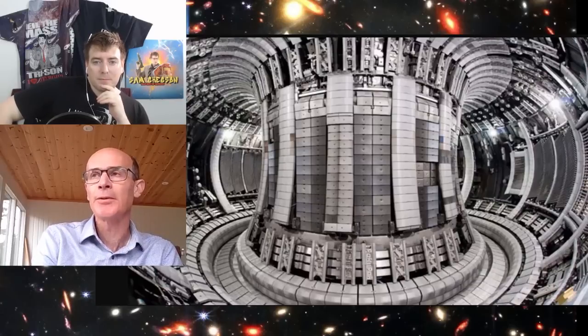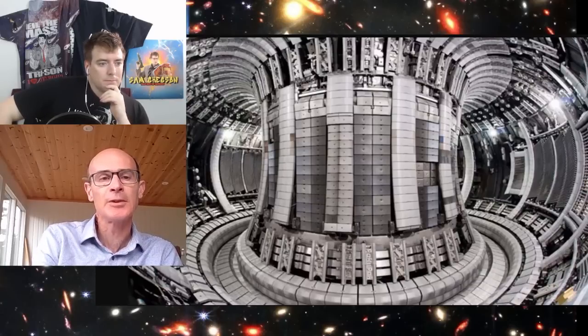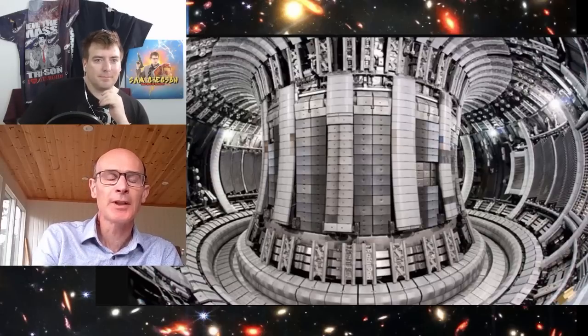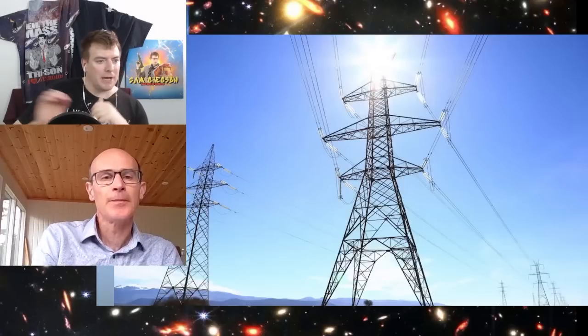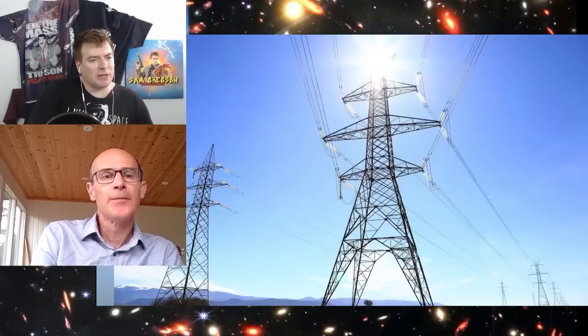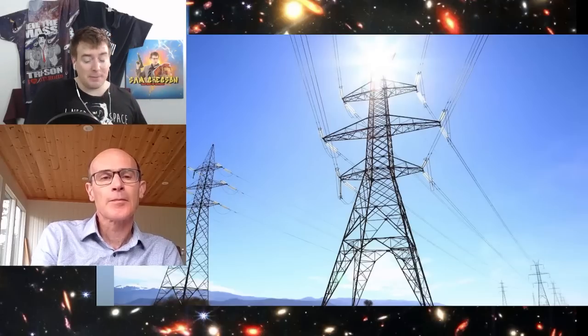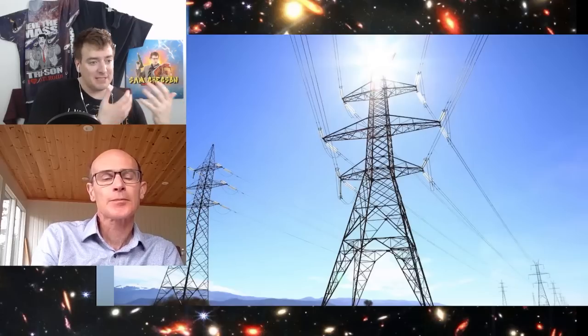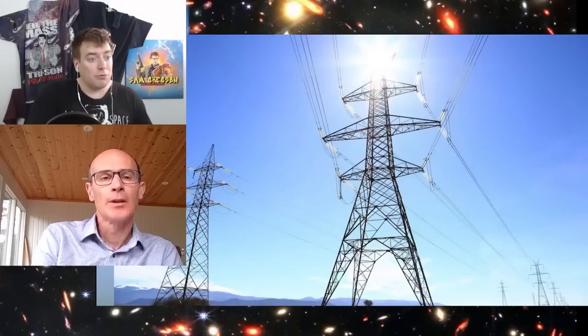It would also, if you could maintain the superconductivity at room temperature, usher in a range of other devices. People have talked about things like low loss transmission lines and things like this. Obviously, when we're passing currents around transmission lines, to some extent they heat up, which is limited by having high voltage, but to some extent they heat up. That's energy loss. That's potential carbon savings, energy savings we could have if we can reduce that resistivity of the material we use in the lines.